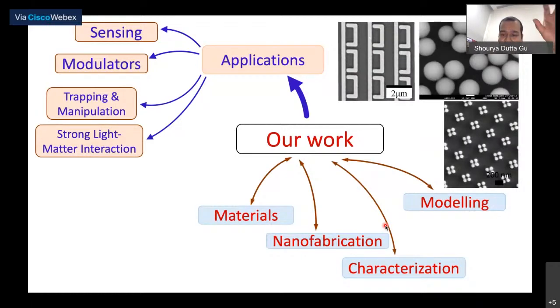So at IIT Hyderabad, we work on different aspects of plasmonics. So we work with the materials, we work with nanofabrication, we work on the characterization, the modeling, and then of course, all our work is directed towards application. Currently, we are looking at sensing and optical modulators. And these are typical images of structures that we have fabricated over the course of time. So these are silica particles, which have been made using Stober's process. These are structures. So each of these dots that you see, the bright regions, cylinders, are gold cylinders with a diameter of around 80 nanometers and a gap of around 20 nanometers.